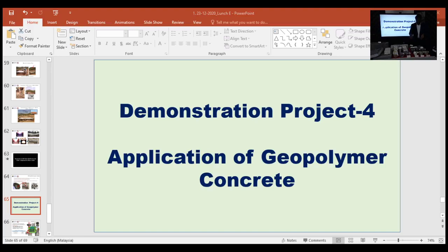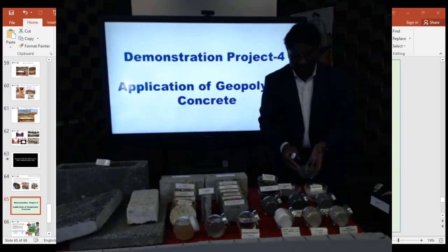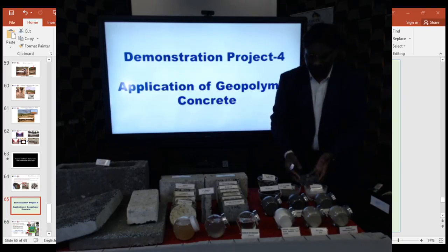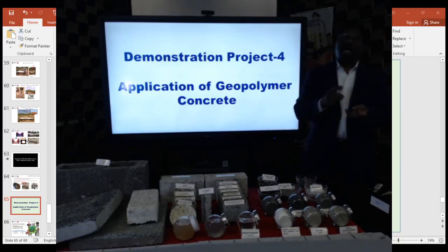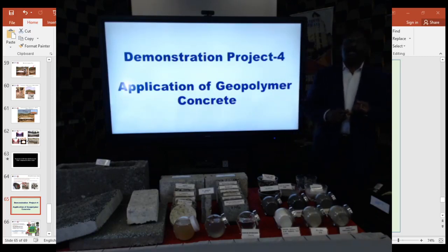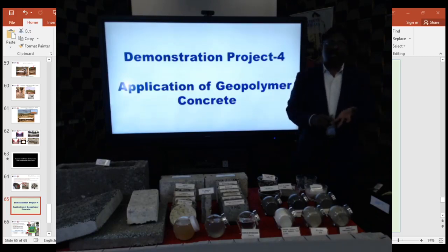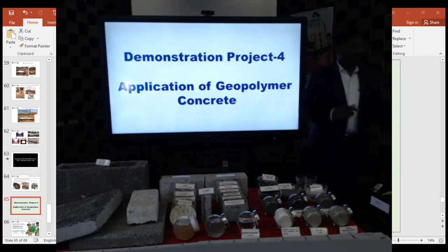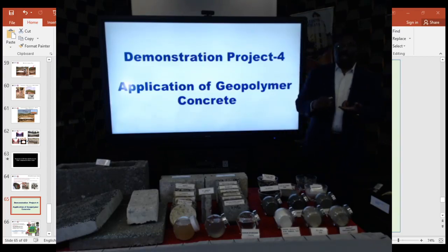We have utilized in this project the palm oil clinker as a coarse aggregate, and we have utilized manufactured sand as a sand replacement for 100%, and we have used these slag aggregates. We have also used ground granulated blast furnace slag as a cement replacement and fly ash as a cement replacement, and we have used the palm oil fuel ash and palm oil clinker powder in this project.